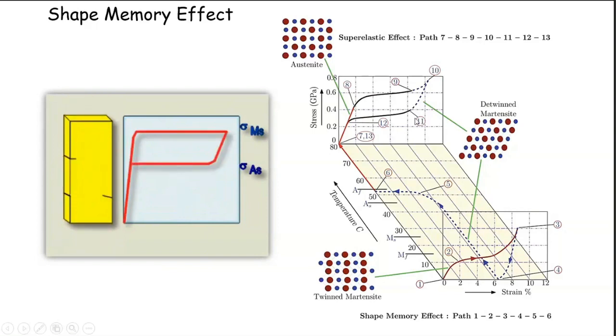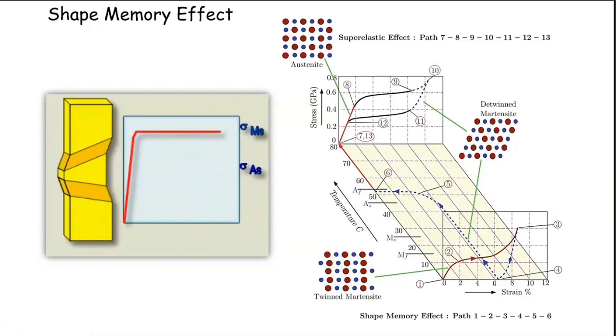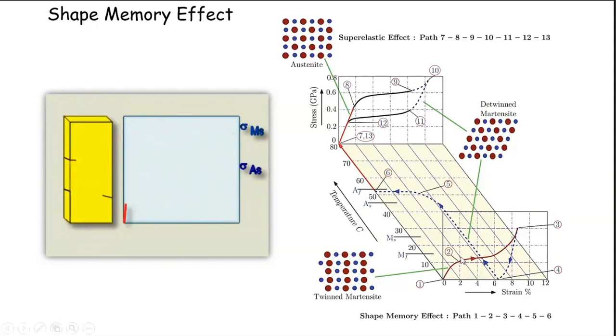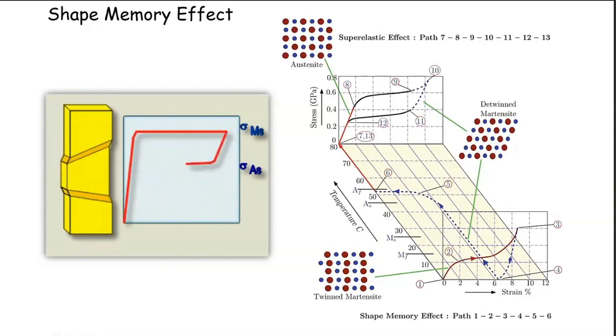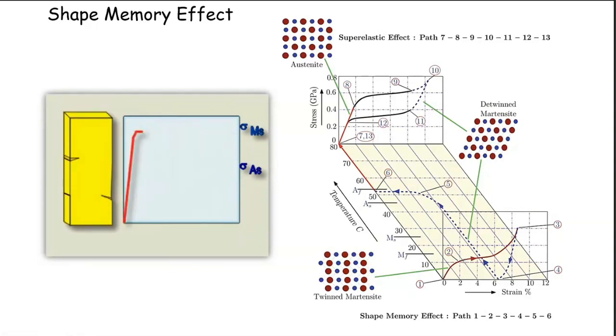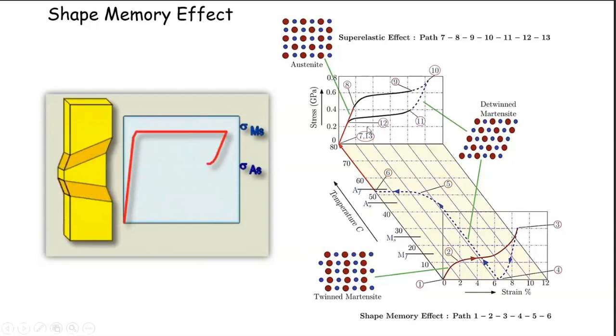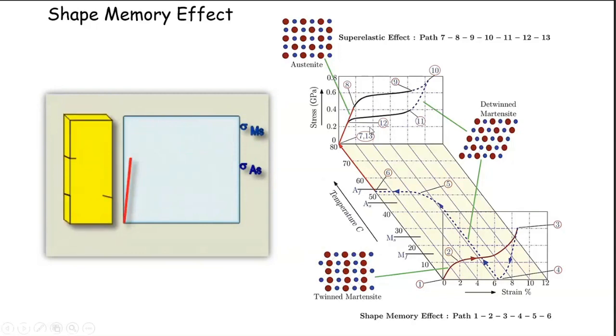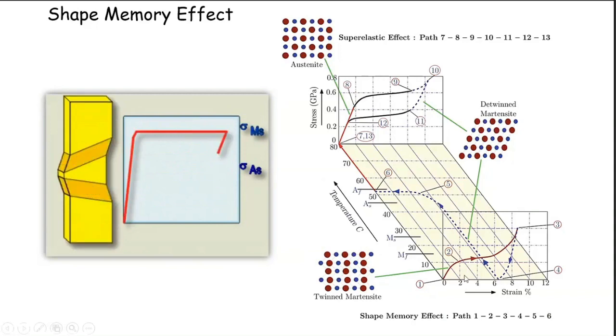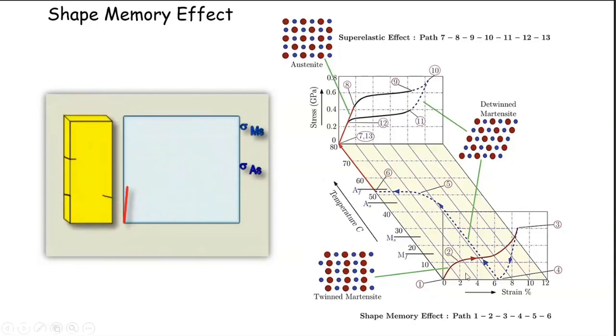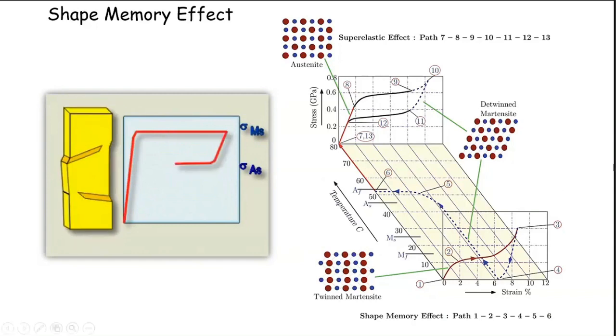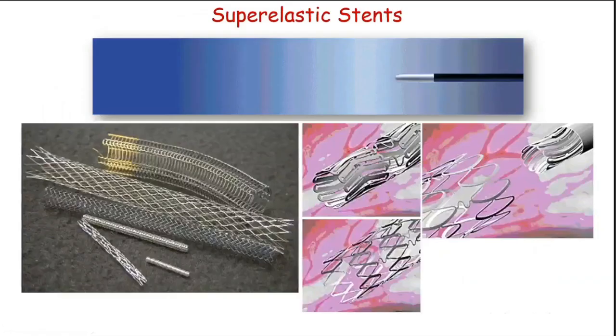So that is about this behavior, and this is referred to as superelastic. And this one, which you have seen in the deformation which has happened in the martensitic condition, is called pseudoplastic. And pseudoplastic, why? Because you're recovering it. This is also referred to as pseudoelastic, but I'll be calling it superelastic, which is how it is commercially applied. So these are superelastic nickel titanium alloys, and what is preferred is if you have it austenitic at room temperature, when you can actually deform it and recover it. And if you had martensitic at room temperature, you would of course have an application at a much higher temperature where you heat it and recover it. So we'll see in the next slide one application of superelastic, which is the superelastic stents.